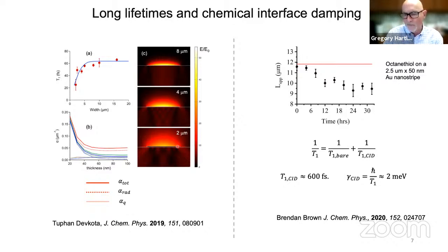And it just sort of seems like we can understand that through a geometric effect, that as we make the structure smaller and smaller, the field from the plasmon at the top of the structure gets more intimately involved with the photonic fields in the glass. So it sort of leaks over into the glass more, and you get better coupling with photon modes in the glass, and so the structures become a bit leakier as they get smaller. It's in the opposite direction of what happens for a particle.